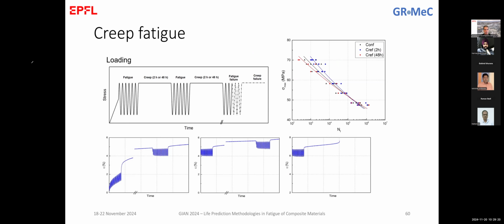So these effects are more or less justified by these observations, and it's quite significant to show that here, for example, we say, okay, it's not very different, but if you see the average numbers of cycles here, imagine at this 70 megapascal of stress, if we get the line for the average, for the black curve here it is around 700 cycles, and the blue curve gives around 2000 cycles. So it's more than twice as much life that you can secure if you apply a creep load for a certain small, short time interval. If you keep this creep for longer times, then you can go down to half of your fatigue life at these high stress levels.